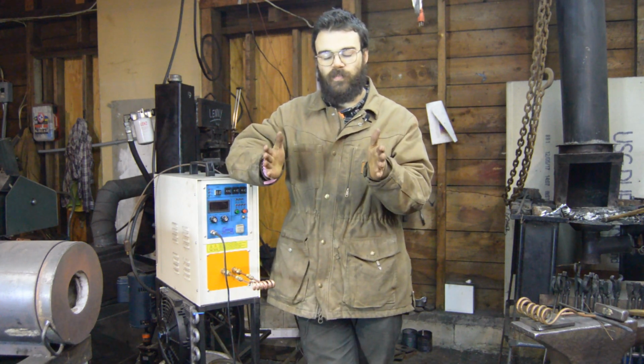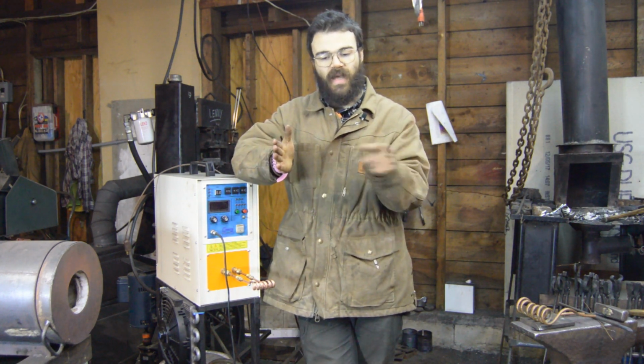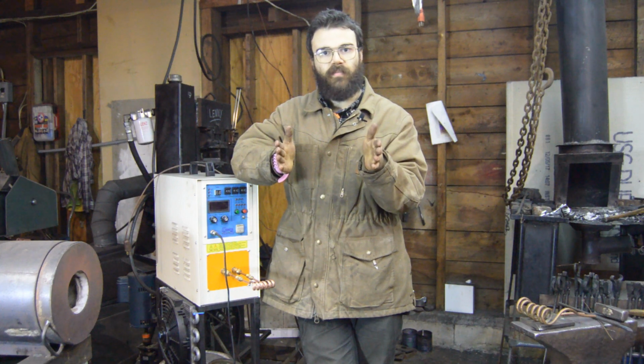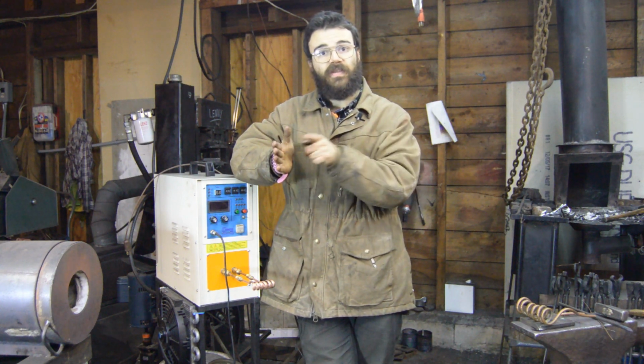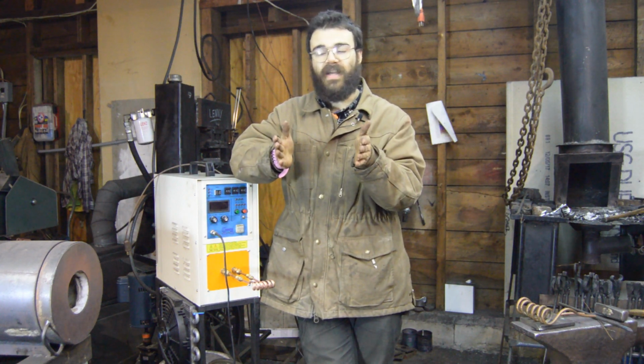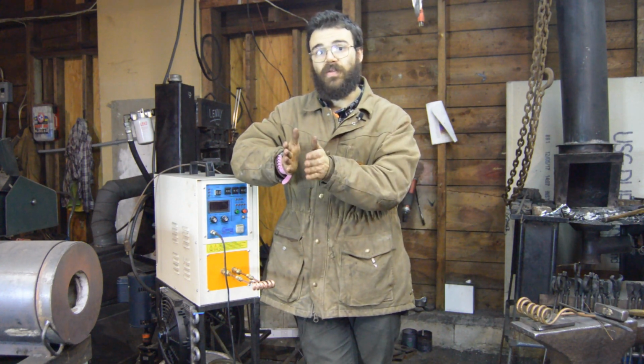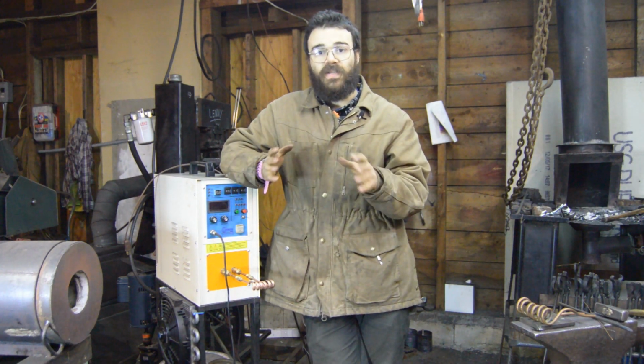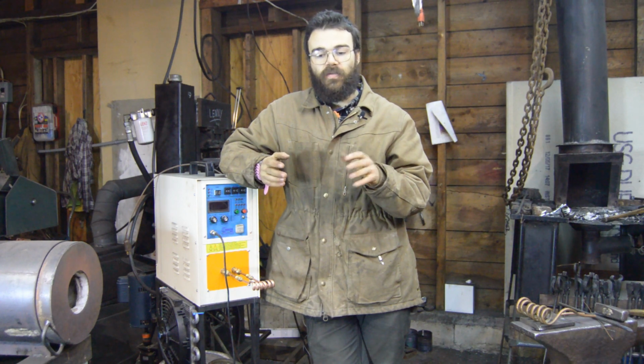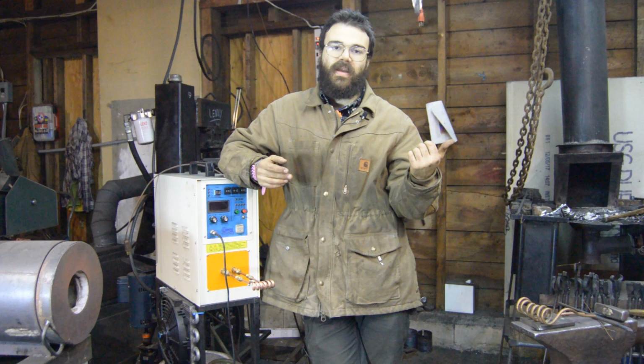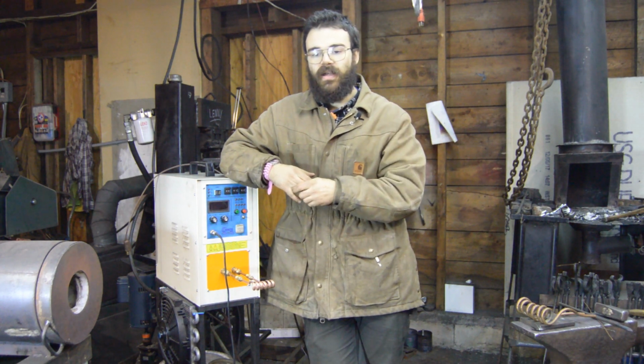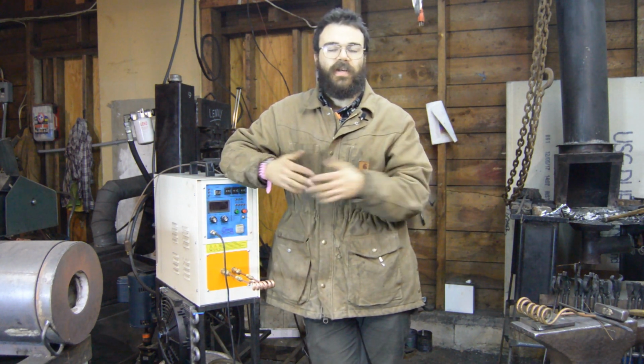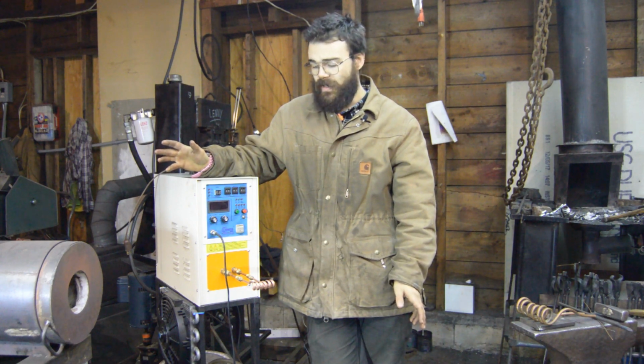You take two flat plates, and again, you pass that high frequency current between them, and it generates an electric field between the two plates, sort of like a capacitor. So if you put an insulating material between, you do create a capacitor. That high frequency current going between the plates creates some sort of molecular agitation, sort of like the magnetic hysteresis effect that I talked about before, that heats up the material through internal friction. That's all I'll talk about for now, about that.